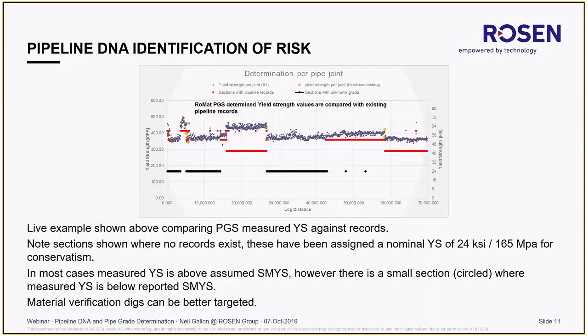You can see in most cases, the measured PGS yield strength is above what the operator thought they had. There is a small section at around 16,000, 17,000 feet where a couple of pipes were below the reported SMYS. This allows the operator to better target their digs, their verification, and their integrity management strategy. If the strength of the pipe was a major concern for them, then obviously they need to look at the lower strength parts of the line first.